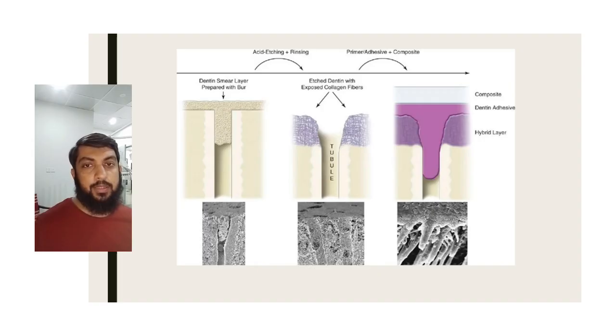This moist bonding technique basically means when you dry it for a prolonged period of time, you have to re-wet the dentine with non-water types of liquids such as isopropyl alcohol, acetone, or your bonding agent. You have to rub it vigorously to make the collapsed collagen refill or re-wet and expand on its own by hygroscopic expansion. The depth of penetration of bonding agent is increased. Bonding strength is improved, so you do not have the problems of prolonged drying.